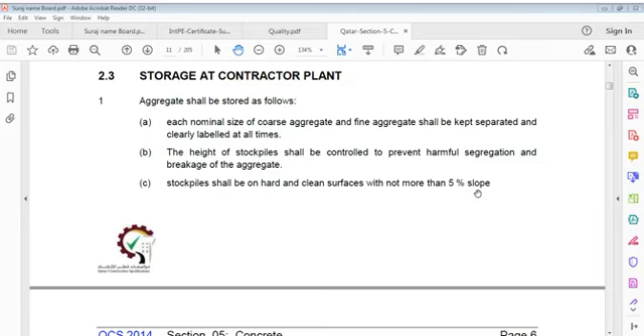I can say storage at contractor plant. Aggregate shall be stored as follows. Each nominal size of coarse aggregate and fine aggregate shall be kept separated and clearly labeled at all times. Height of stockpiles shall be controlled to prevent harmful segregation and breakage of aggregate. Stockpile shall be on hard and clean surfaces, with not more than 5% slope. So this is stockpiles, 5% slope. 5% means 5 in 100, that is 1 in 20.